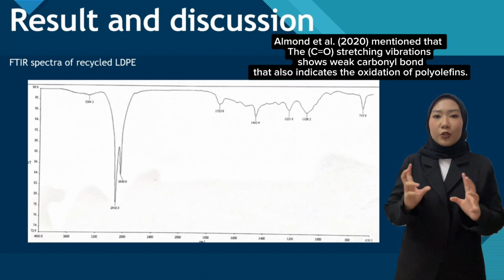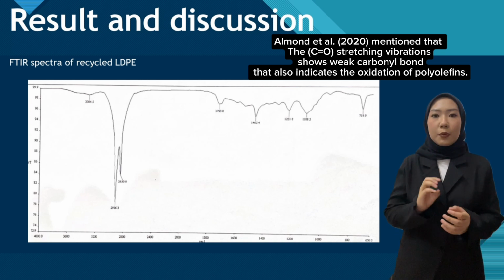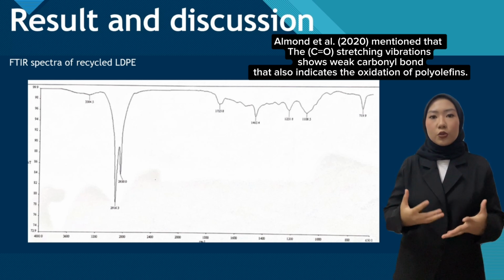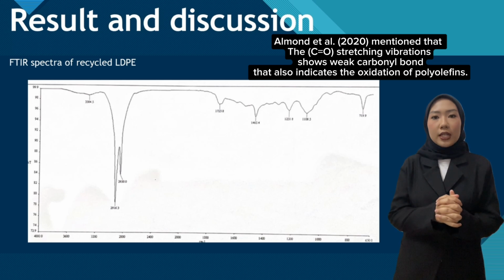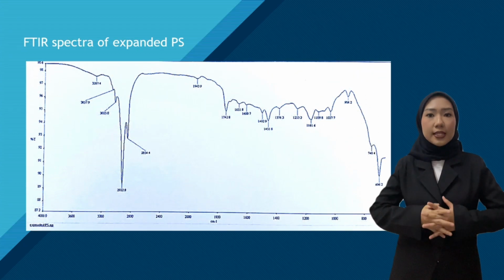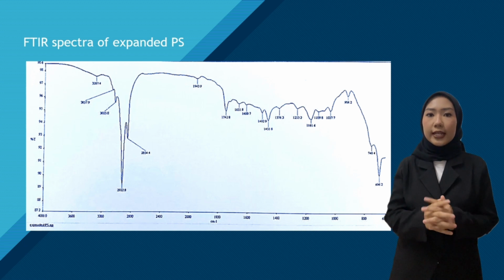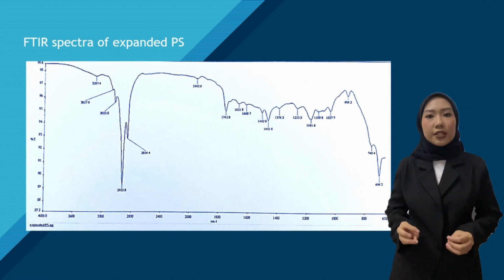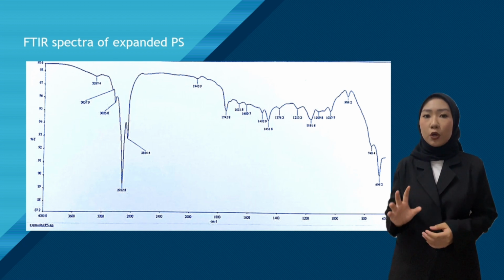Almond et al. 2020 mentioned that the C double bond O stretching vibration shows a weak carbonyl bond that also indicates the oxidation of polyolefins. The FTIR spectrum of expanded polystyrene shows absorption peaks at 2922.8 and 2854.4 cm inverse that show the stretching vibration of CH bonds in the blowing agent.